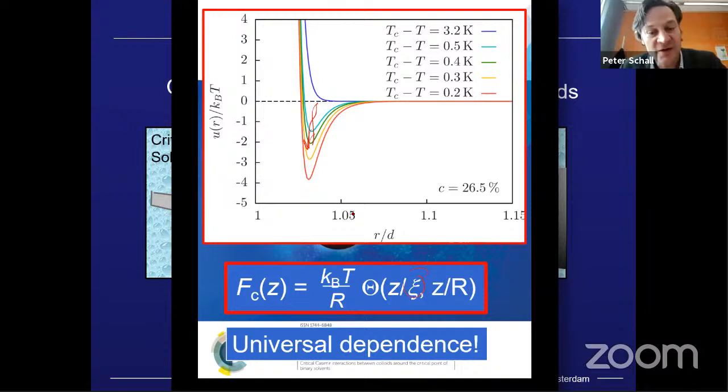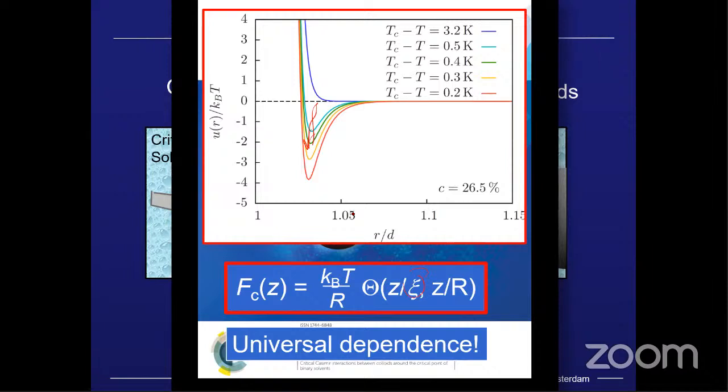You can make it larger, which means, I think, that in the images I showed you of the chains, you will not see that distance. It's below optical resolution. But I do believe that at any point in time, you do have these critical fluctuations between these patches. So they're not really physically attached in a sense, but there is still this solvent in between. Okay, yeah, because 20 nanometers is large compared to the length of molecular interaction, which is only 1 or 2 nanometers at most.